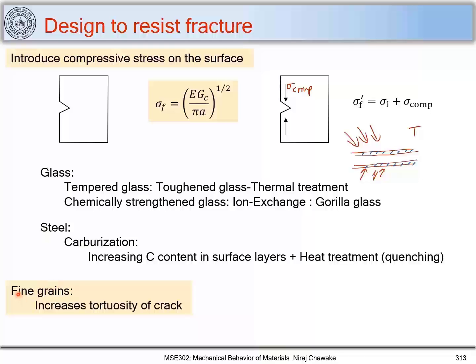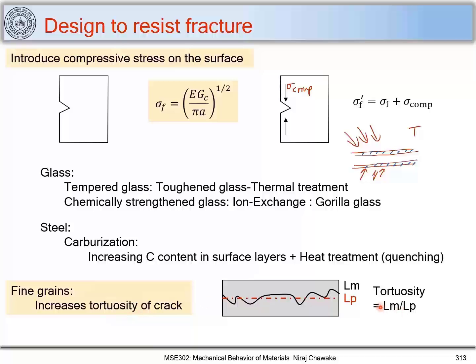Another way to increase the fracture toughness is to make the grains finer, which increases the tortuosity of the crack. And what do we mean by tortuosity? Let's say you have this material and the crack will propagate in this fashion. I call this total length Lm. Now I can project this crack along this direction, and I call it the projected length, Lp. So tortuosity is defined as Lm, that is the total length of the crack, divided by the projected length. If the tortuosity is higher, that means the crack takes a longer path, that Lm is more compared to Lp. And fine grain does increase this tortuosity, and thus you get an increase in the fracture toughness.